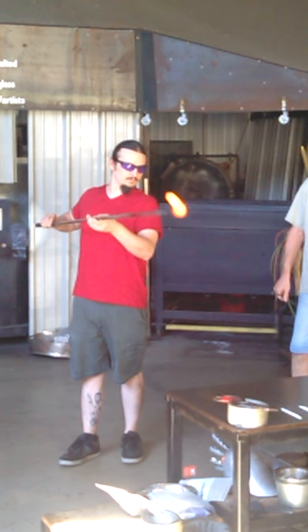This is water-clear glass — it's just orange because it's at 2,100 degrees and it's glowing. At that temperature, it's about the consistency of honey as it comes out of the furnace. It's going to go through progressive stages of firmness as it approaches its freezing temperature, which is around 950 degrees Fahrenheit, at which point the glass will be just as firm and fragile as room temperature glass.